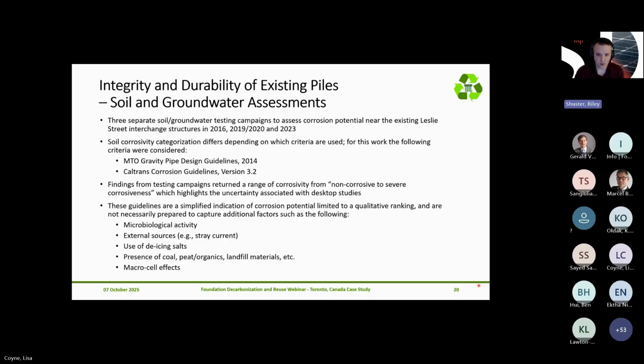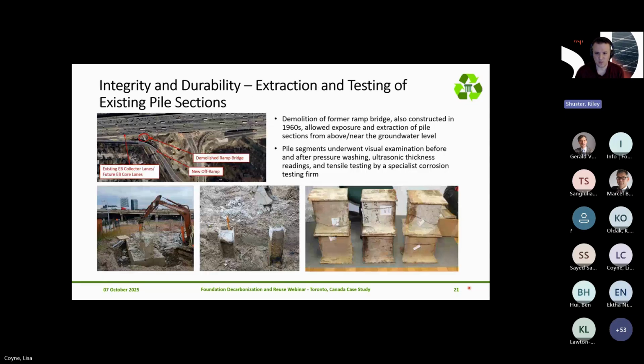Generally the findings from these testing programs that were completed on this project have suggested soils with corrosivity in the range anywhere from non-corrosive to severe corrosiveness. Quite a wide range, and these guidelines are typically qualitative in nature. They provide a ranking and then prescribe values to use for corrosion allowance. There are additional factors that are not always captured, things like microbiological activity, stray currents, use of de-icing salt that may change the characteristics of the soil over time, presence of organic material or macro effects from the different soil layers or groundwater conditions. So generally just trying to highlight some of the challenges that might be associated with relying solely on a desktop type study.